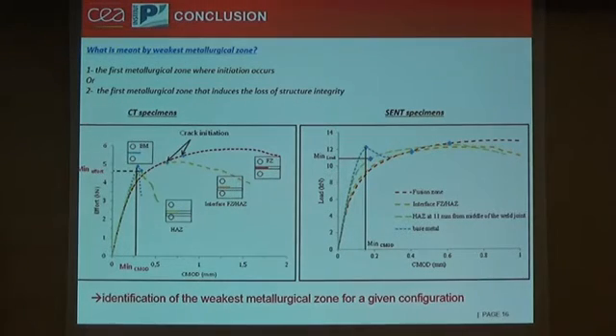To conclude on the objective of this presentation, the weakest metallurgical zone, first of all, we have to define what is meant by weakest metallurgical zone. Is it the first zone where initiation occurs, or the first metallurgical zone that induces the loss of structural integrity? Here I compare the CT specimens with the SENT specimens, and as we can observe for the imposed displacement loading, the base metal and the heat affected zone are the two metallurgical zones that initiate first, and clearly if the crack initiates in one of these two zones, it will induce the loss of integrity of the structure, as there is little involvement of plasticity in crack extension.